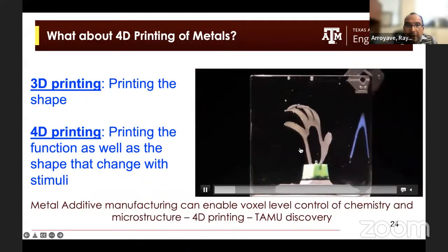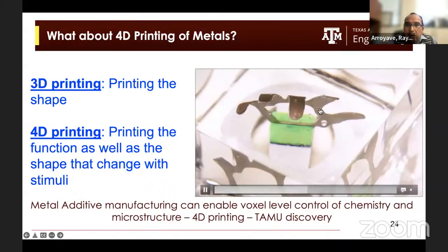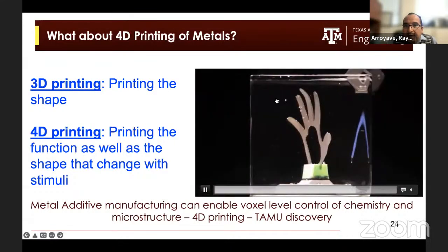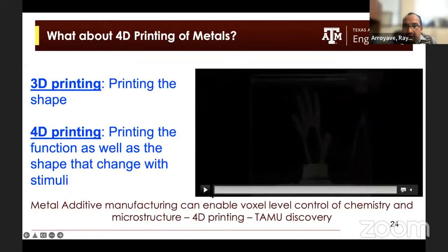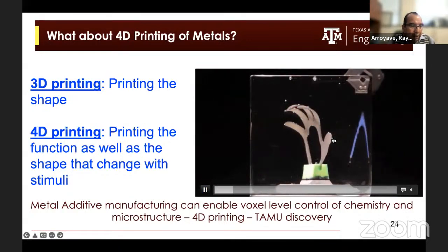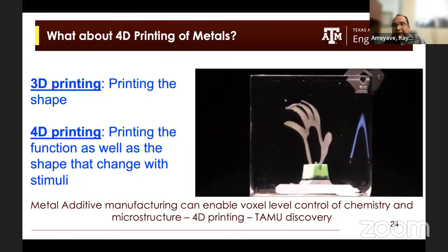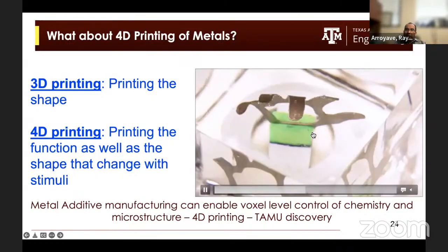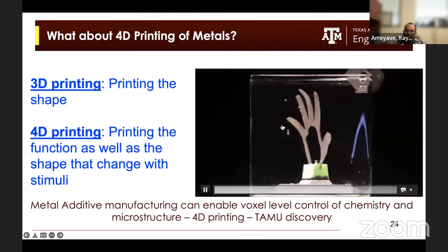This is a video that we have where we printed a hand at Texas A&M, and every single finger of the hand was printed with different process conditions. And as you can see, in this hand, different fingers are actuated at different times, right? This is not water, this is actually glycerin. It turns out that if we try to do this with water, we will see a lot of boiling and a lot of bubbles, so we wouldn't get a nice picture. So we basically had to figure out what type of liquid to use, and we settled on glycerin to try to visualize this actuation response with minimal visual disruption, right?